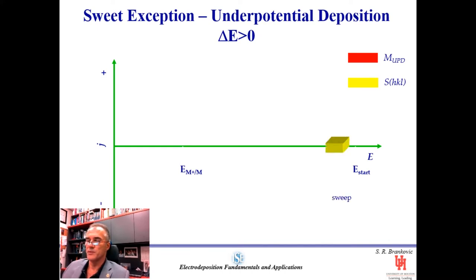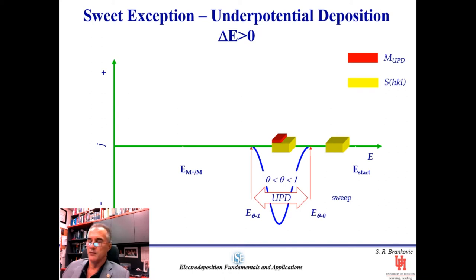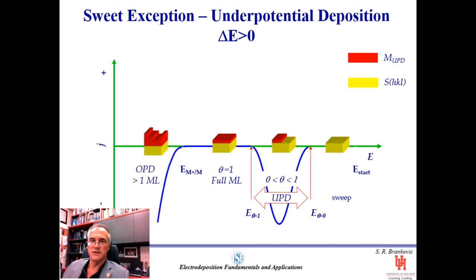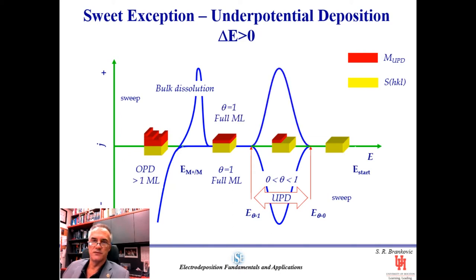Basically, if we sweep the potential from the positive side towards the negative, we will soon encounter a cathodic peak, which represents the formation of the copper UPD monolayer. Then, if we continue further, the UPD monolayer may change its structure and density, but eventually when we exceed the reversible potential for copper, we will start depositing bulk. When we reverse the sweep, going in the anodic direction, we can dissolve this bulk copper and we are going to stay with a copper monolayer on gold. And then if we continue further in the same direction, we will be dissolving the copper monolayer.